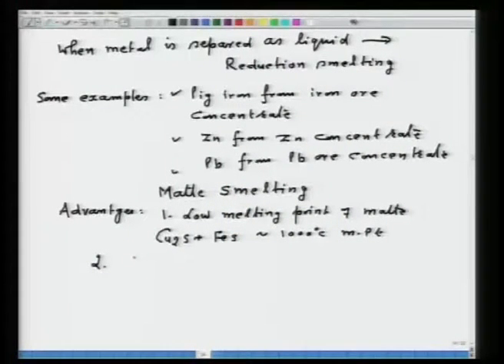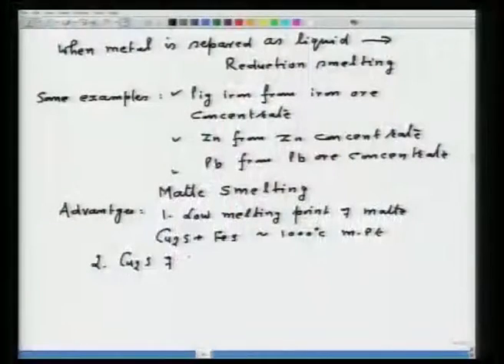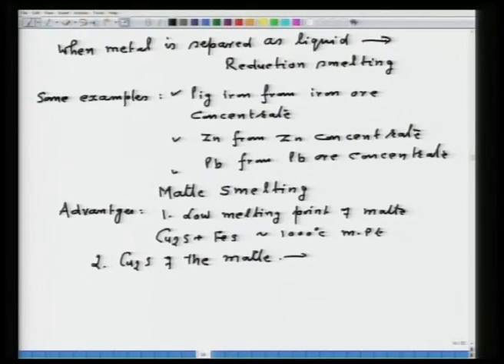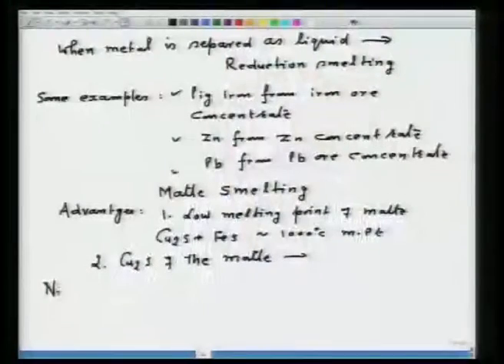Also, another advantage is that the Cu2S which is contained in the matte does not require any reducing agent, in the sense of carbon or such reducing agents. By blowing oxygen you convert part of it to oxide, and then it is a sulphide-oxide reaction that leads to the production of copper. That is another advantage of matte smelting. This is for copper mattes. Similarly, nickel mattes,